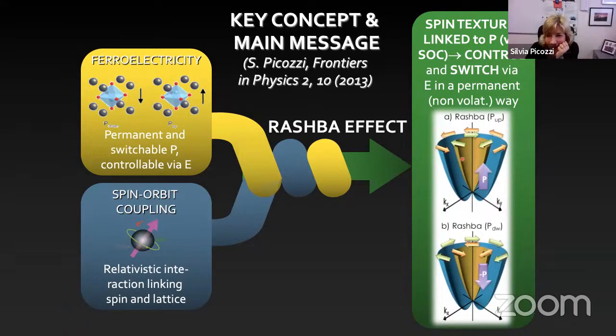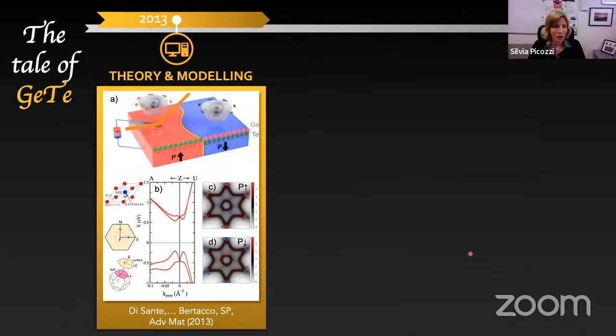Yeah, so basically, going back to the effect here, you have a certain spin texture which is bound to the direction of polarization, which implies that if you switch the direction of polarization, also your spin texture will be switched. And so you basically achieve a control of your spin texture, which is non-volatile, because a ferroelectric, if you switch the polarization, it will not go back to a normal unpolarized state. It will stay polar, and so it will keep its spin texture. So since one of the dreams of spintronics is the electric control of spin degrees of freedom, this could provide a way. And so our material of choice since, I don't know, 2013 has been germanium telluride. And in our first proposal, we used it really to show that you have a large Rashba effect, but not only that, the important thing here is that when you switch the direction of polarization, you also switch the spin texture.